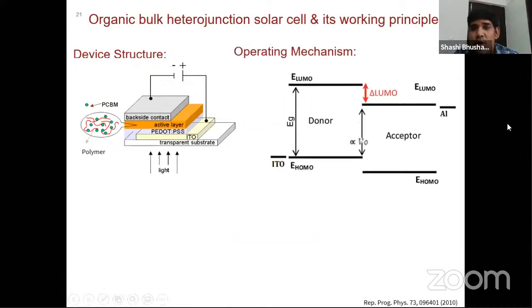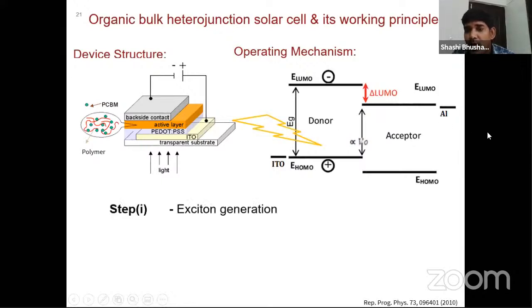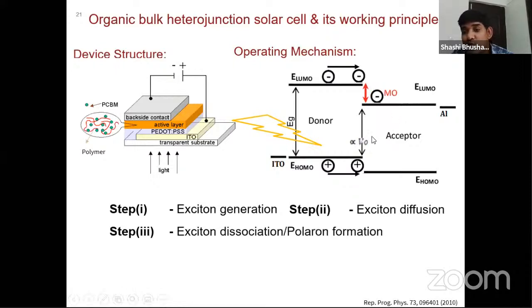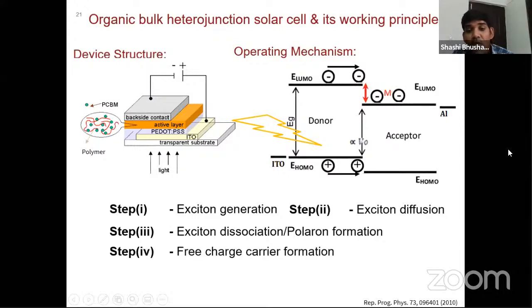So if you see here, what happens in the operation mechanism of a solar cell: this is the donor material and this is the acceptor material. If light shines, there will be exciton generation, and after that exciton diffusion takes place, which is in the range of 20 nanometers, and then it reaches the acceptor by the difference of electric potential at the interface. It forms polarons, polaron electron and polaron hole, and after that there will be free charge carrier formation, and then it moves towards the respective electrode. One is here and another one is here.